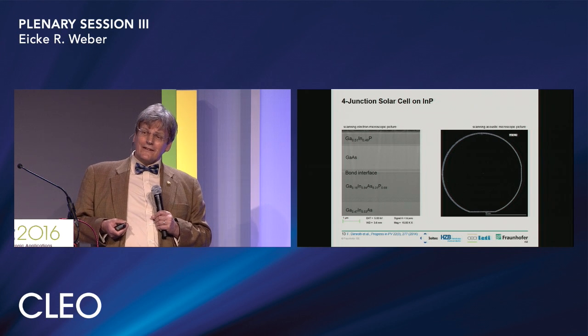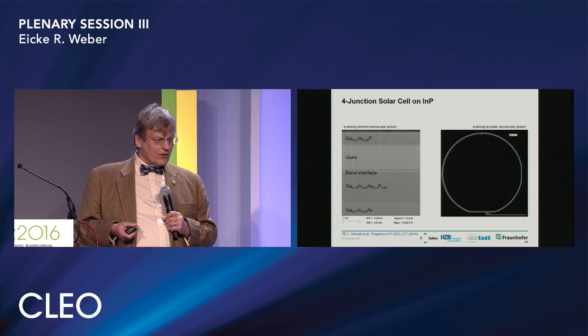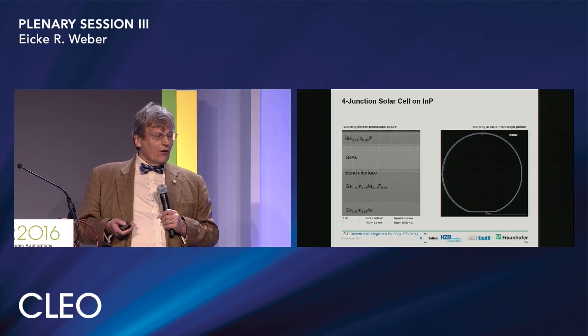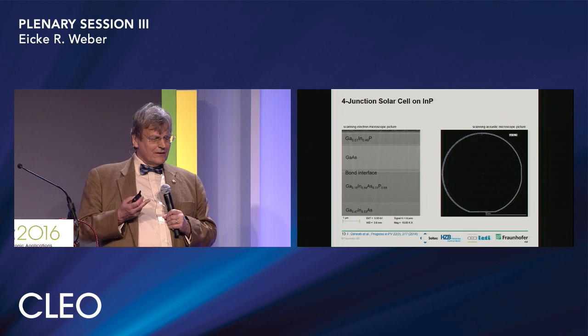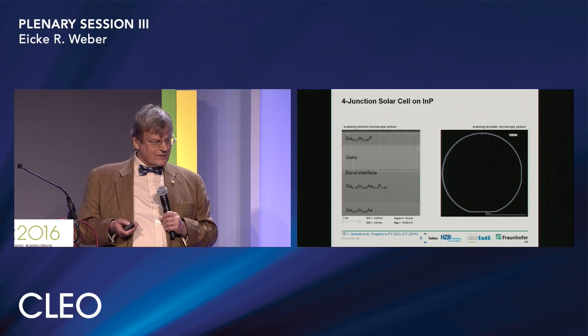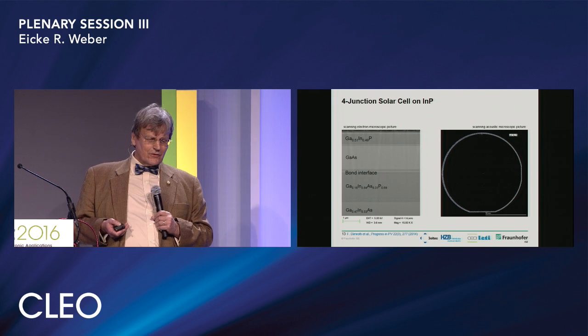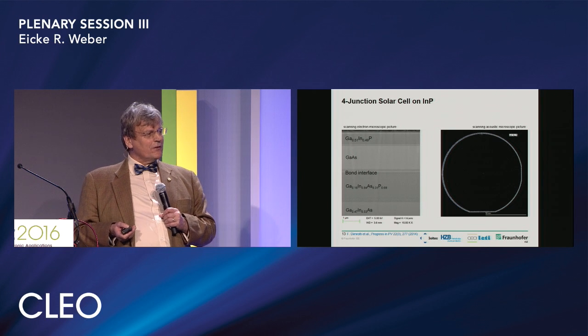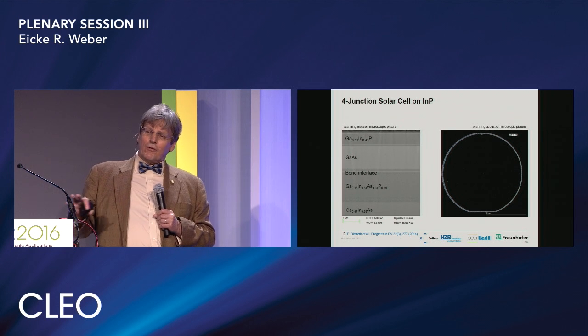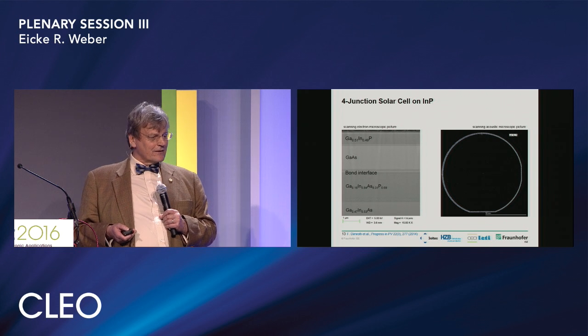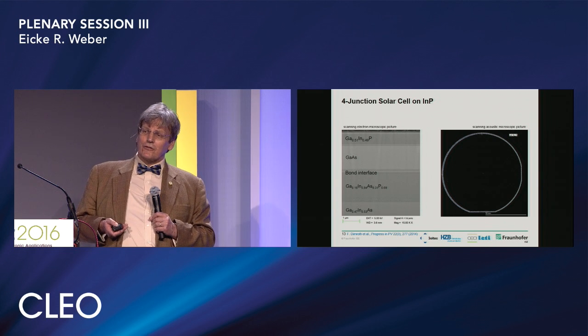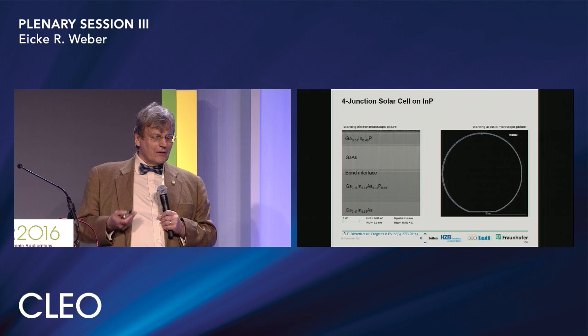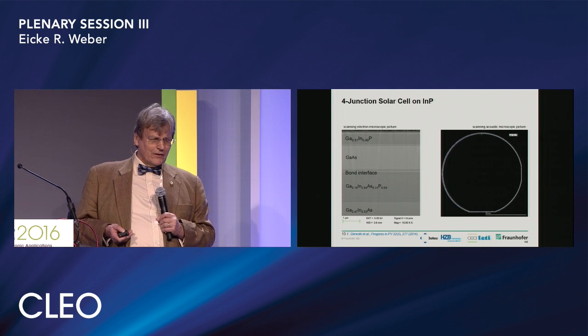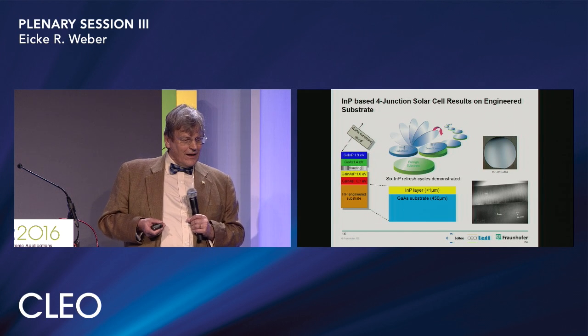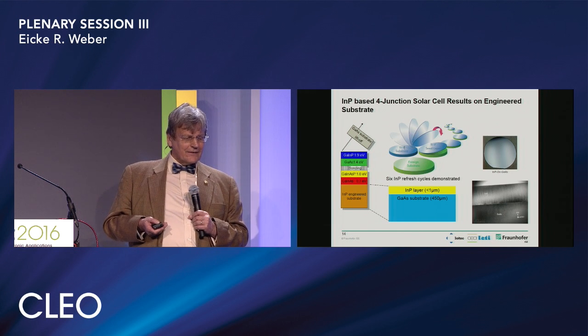The really most exciting structure, which is the holder of the current world record, is a 4-junction solar cell on an indium phosphide type structure. You see here the scanning electron microscope cross-section. In the scanning electron microscope, you of course recognize only large areas. Very critical for bonded structures is to look at the quality of the interface, if there are bubbles and things like that, and therefore the scanning acoustic microscope turned out to be a very valuable characterization tool to see the quality of these layers. And this is how these indium phosphide-based cells are being made.